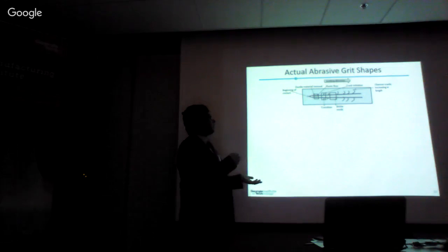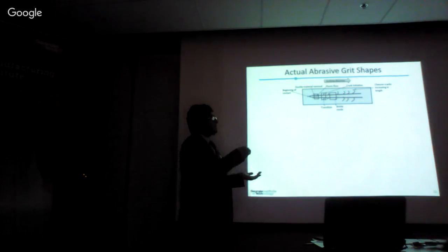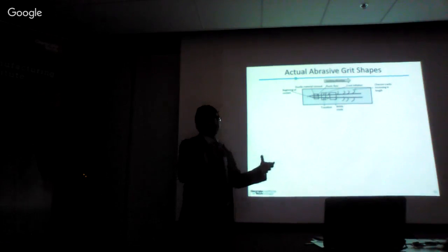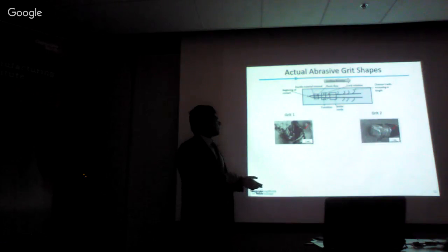Now, a typical scribe created by this process of increasing depth of cut would start from a point of contact, have a region of ductile material removal, and then transition into brittle fracture. And we find the critical depth of cut here where the first crack appears by the confocal microscope. Even deeper, there will be larger cracks, like chevron cracks here, and the width of the groove will increase because more abrasive is interacting with silicon and removing material.